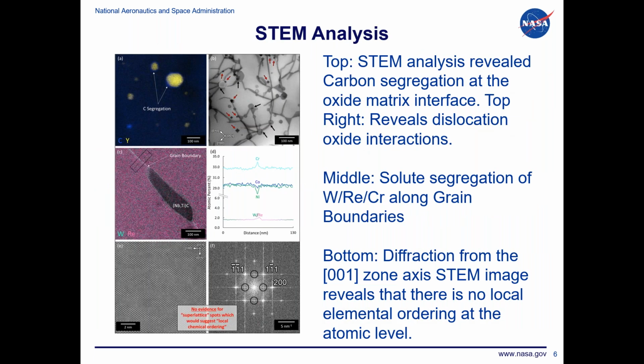And so we'll dig into some of the microstructural results. As you can guess, we were able to take that coated powder and print with it really well, and we were able to disperse the nano oxides during that printing process. And so these are some of the interesting microstructural features that we've seen in GRX 810 that might give reasons for why we're seeing so much better properties than even other ODS alloys that we've tried to print recently.